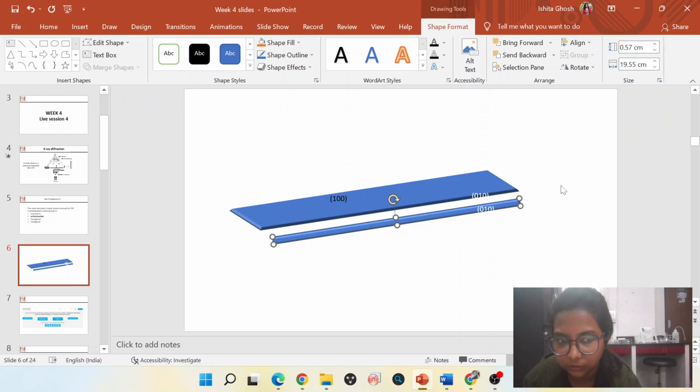So you have to be careful because when polymorphs come in a mixture, in the PXRD pattern also there will be a mixture. If you take a single crystal and you do the single crystal data, when you solve it, you will get a simulated powder pattern. You know, right?